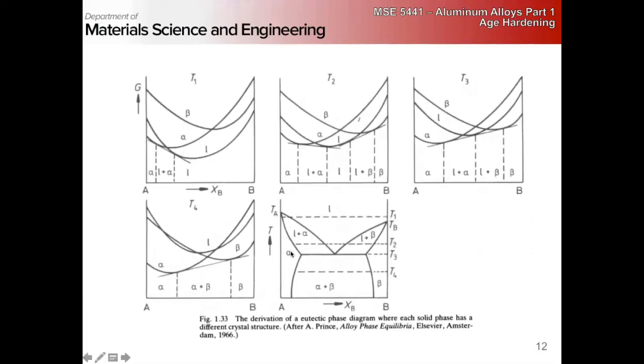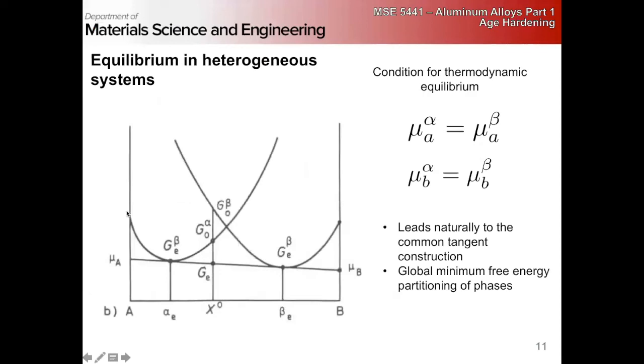And I'm sure in thermo you did the exercise where you looked at different parts of the phase diagram and looked at how we go from the free energy curves to the phase diagram. And the important one is the eutectic. So at different temperatures, if I'm at the eutectic composition here... I should make one more point. Basically, what this tells us here is if I'm in this composition range, I'm going to be all alpha. If I'm in this composition range, I'm going to be all beta. If I'm in between, I'm going to have a mixture of alpha and beta. That should be self-evident, but I wanted to just reiterate it.